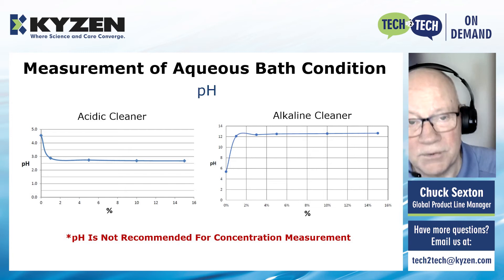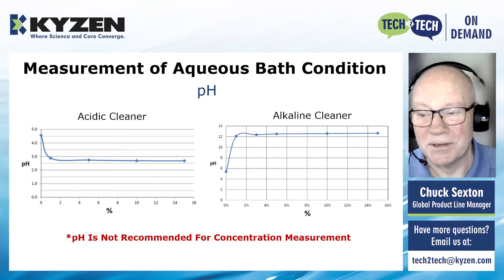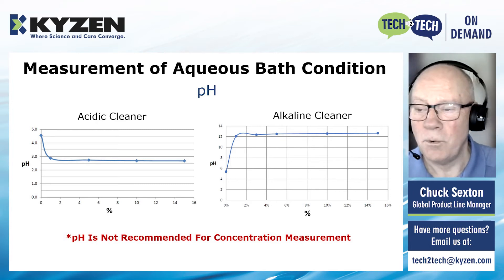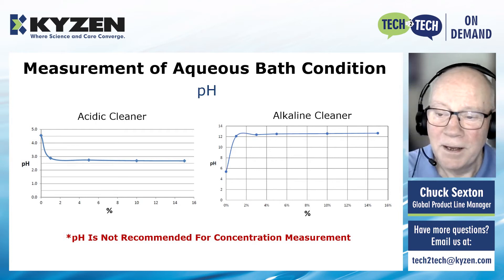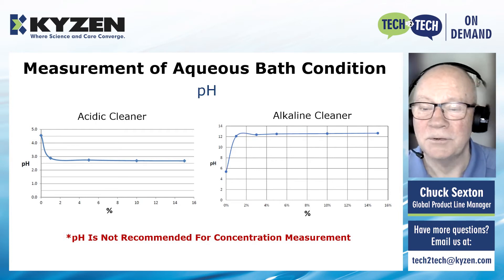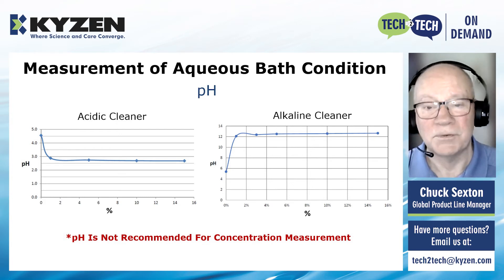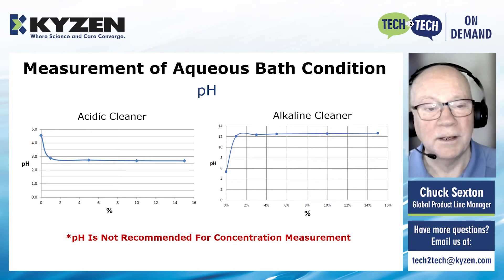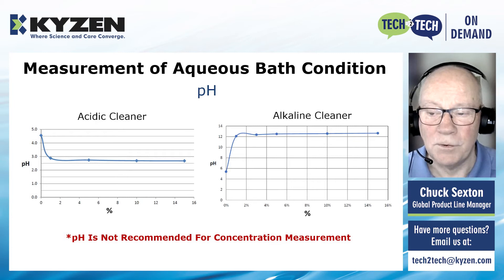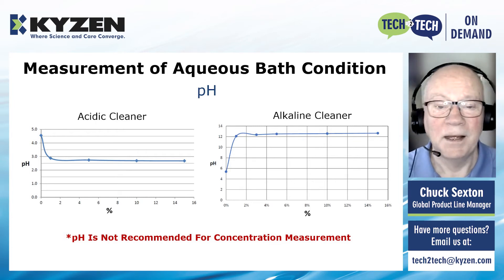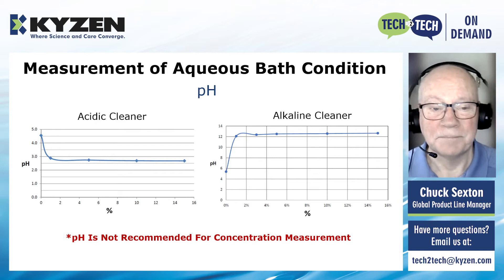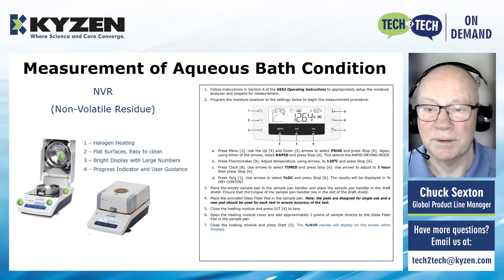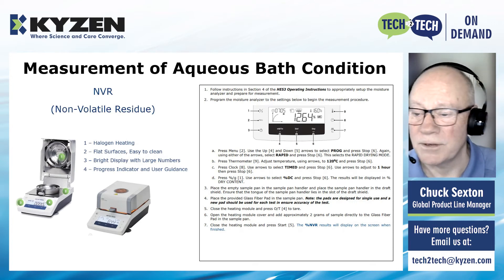Last and least for measuring bath concentration: in my 21 years at Kyzen, about once a month I get the question, can I use pH to measure the concentration of our cleaning chemistry? The answer almost always is no. A couple of graphs of a typical acidic cleaner and typical alkaline cleaner show that over about 1% concentration, the curve flattens out. So pH is not a good method — we almost never recommend it for controlling or measuring bath concentration for cleaning products.